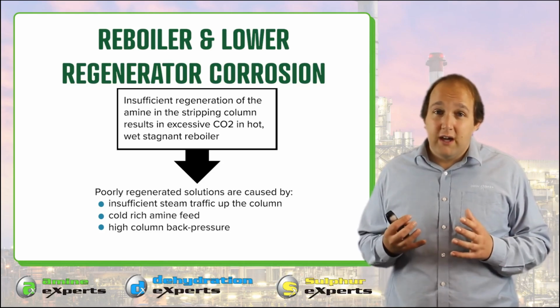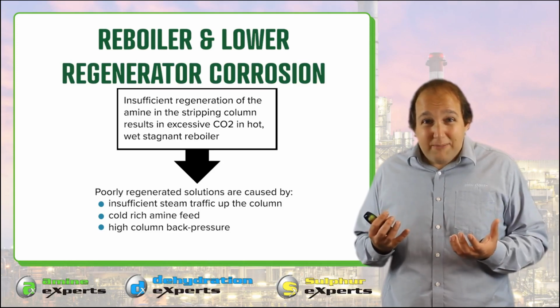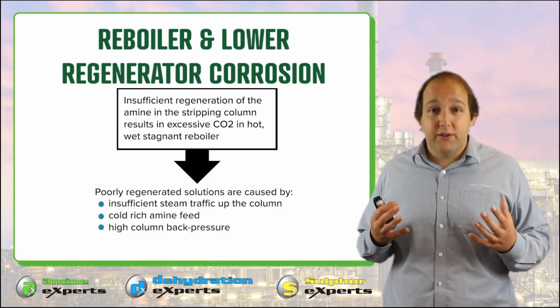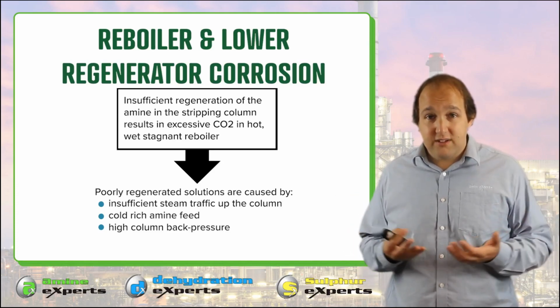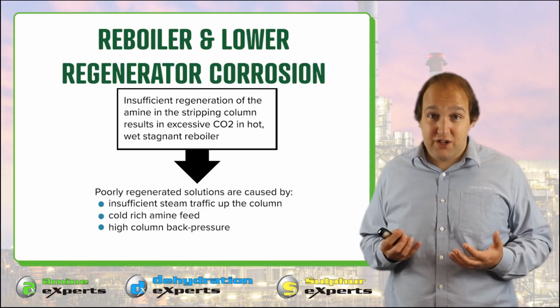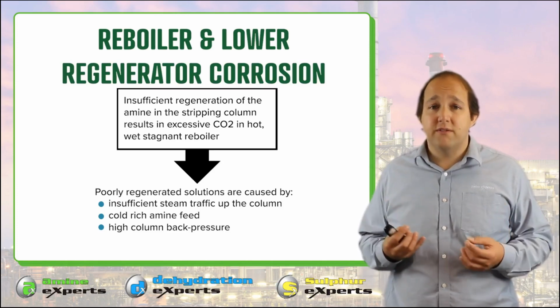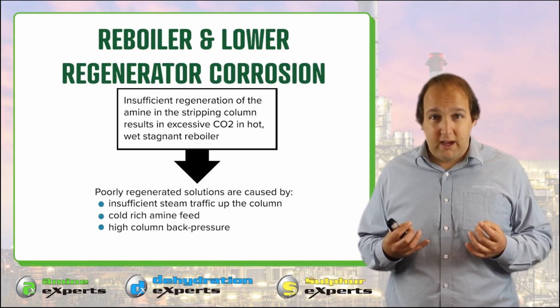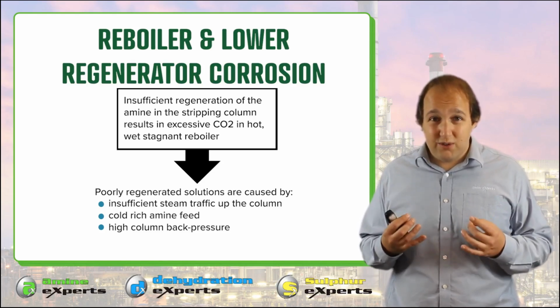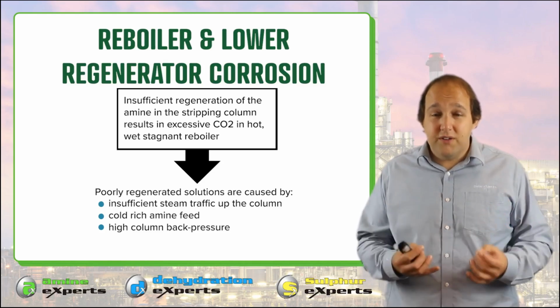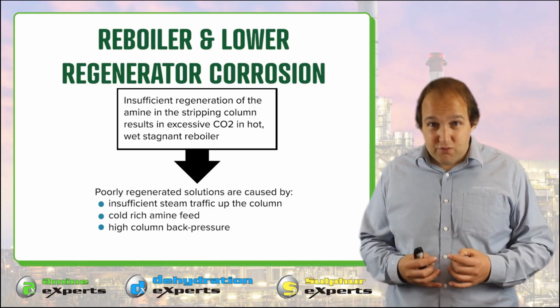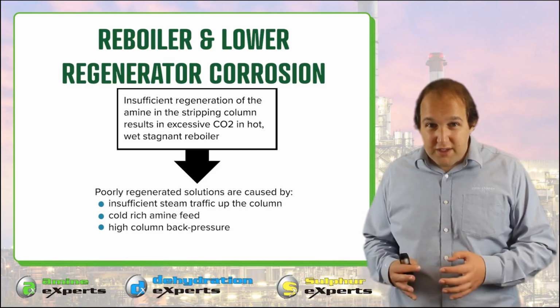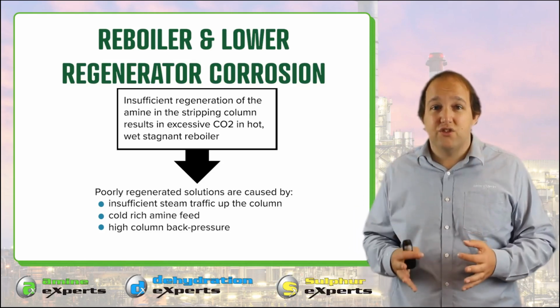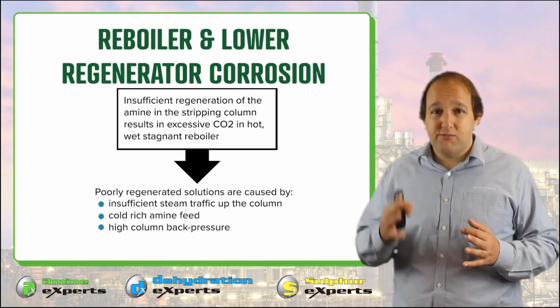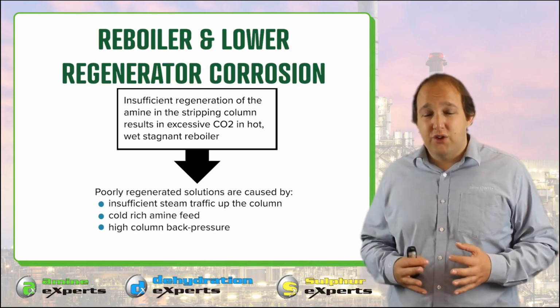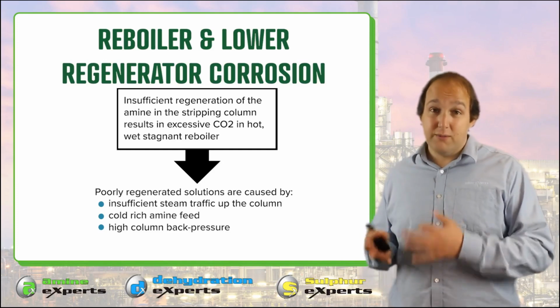And this CO2, when it gets trapped in stagnant areas, especially among your reboiler tubes, where it's not as easy for gas to escape from the liquid as it is on a tray in the regenerator, say, can result in very aggressive corrosion. So really this corrosion mechanism occurs when you are stripping the bulk of the CO2 from your amine in the bottom of the regenerator column and in the reboiler, rather than in the main section of the regenerator column. You want a nice even stripping profile with CO2 being removed throughout the column. You don't want to be doing a lot of stripping in your kettle reboiler, for instance.